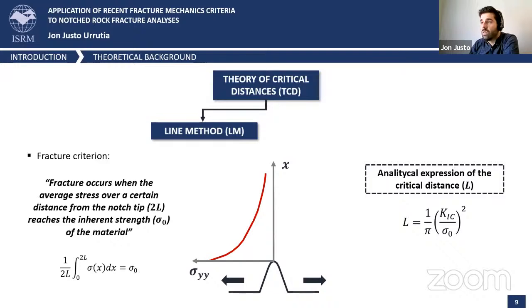The second one, the line method, states that fracture occurs when the average stress over a certain distance from the notch tip, which in this case is 2 times the critical distance, reaches the inherent strength again. So in this case, instead of analyzing the stress at a certain distance, we need to analyze the stress average over a certain distance. Well, the expression for the critical distance is the same.